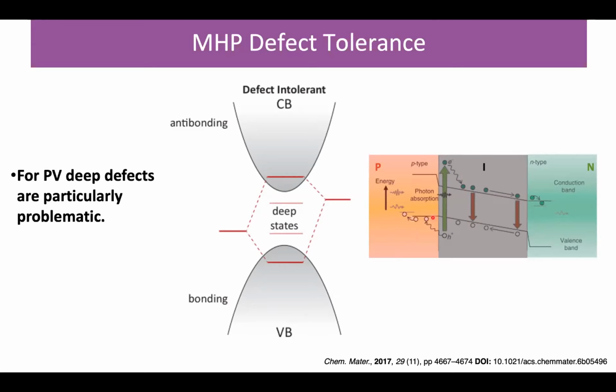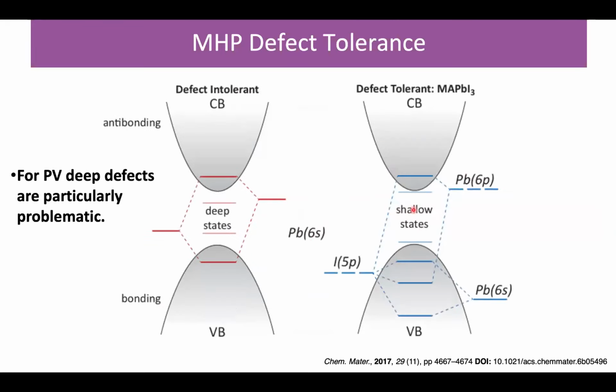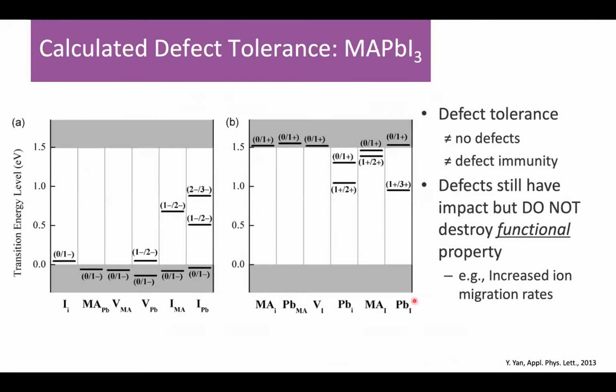However, in the case of a system that we would consider to be defect tolerant, as we have in the metal halide perovskites, instead of having states that are deep in the gap that enable recombination, when we create a vacancy or an interstitial, the location of these defects ends up being either in the conduction and valence bands themselves, keeping the electronic gap very, very clean, or they're very, very shallow, right at the band edges. These are some calculations, and it turns out there are some deep defects that we can make in a lot of these metal halide perovskite systems, but it turns out they're very hard to make. That is to say, their formation energies are quite high, so when you put them down, they are not the predominant defects that you essentially realize in a film.